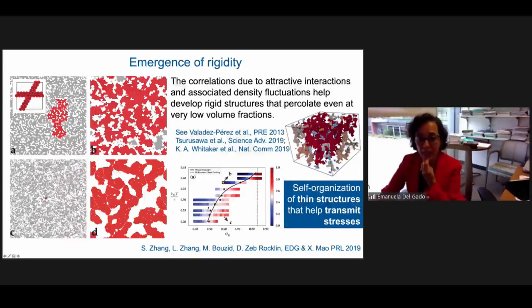And so we could see that, in fact, these correlated processes can favor the formation of smart thin structures, smart because they are specifically optimized to transmit stresses. The fact that they're thin is important because then they can grow and span the system and favor the presence of a percolating network, even with a very small amount of solid material, so solid particles at hand. So with a very small amount of elastic connections that are there.